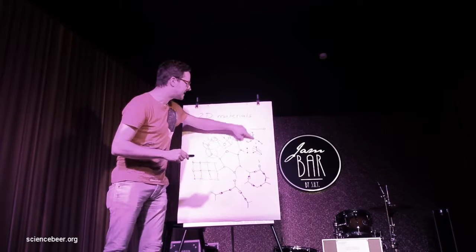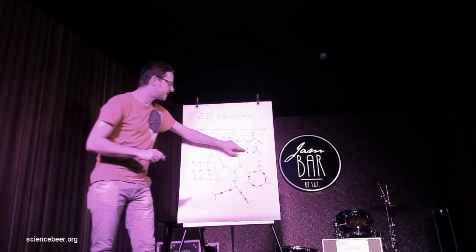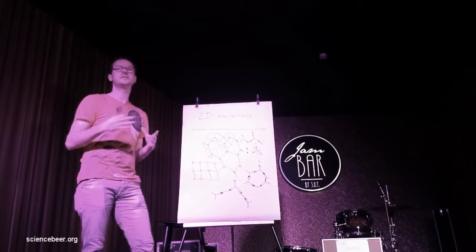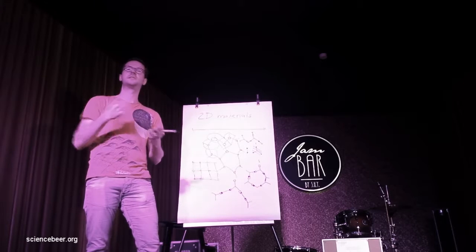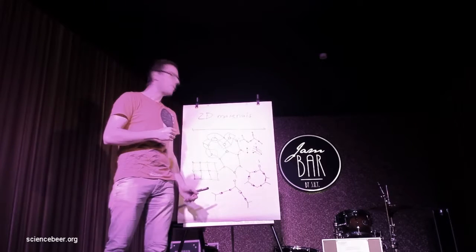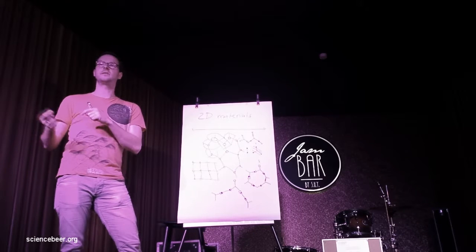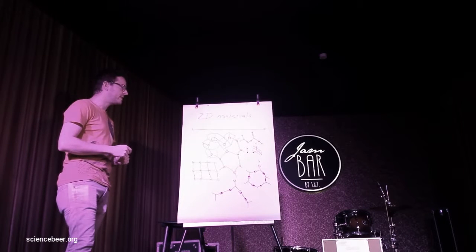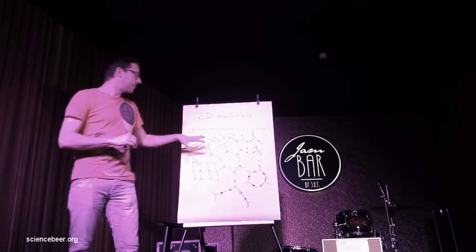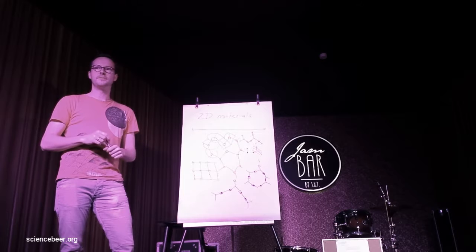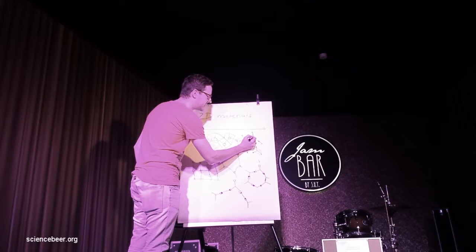By altering the molecule size or adding a spacer, which can have different lengths as well, I can alter the pore size, the density, or tailor-make the volume inside of these materials. So this is one method to tailor-make the material so that it has in the end the properties it should have. The other one is atoms inside. All my material is based on carbon. So it's organic materials, it's metal-free, but we can put inside some nitrogen.